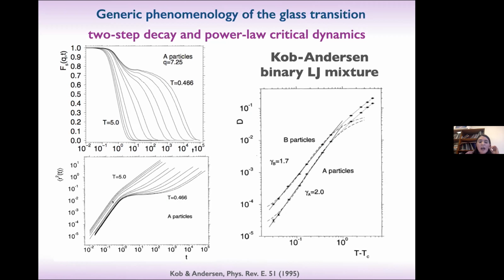Here is the self. And the mean square displacement also shows this typical behavior that I showed you before. And I put it here just for completeness. This power law dependence of the critical dynamics in the density correlators also manifests as a power law dependence of the transport coefficients, like the long time self-diffusion coefficient or relaxation time close to the transition. Then there will be deviations at even lower temperature, but to describe the approach to the transition, the mode coupling theory is quite accurate. You see that you have here in the Lennard-Jones mixture several orders of magnitude where the theory can describe the data, the numerical simulation.